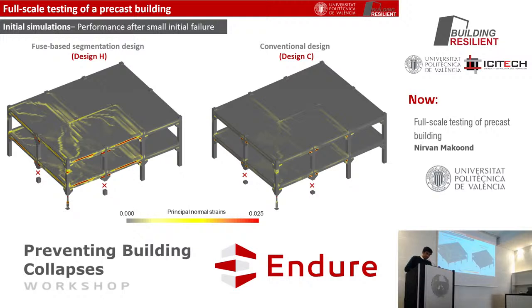Okay, so we performed some simulations for fine tuning the designs, and here we see the result after an extremely small initial failure, one for which load redistribution could still avoid the initiation of collapse. On the left I've shown the principal normal strains in the case of the fuse-based segmented design, and to the right, the conventional design. As we could expect, the fuse-based segmentation design is slightly more strained for this case, whereas the conventional design with more continuity is less strained because it distributes the load better.